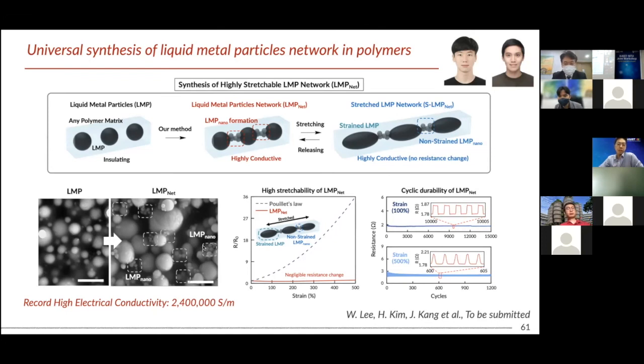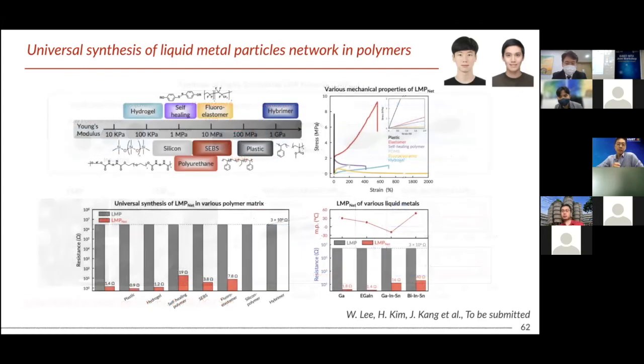And this resultant network showed really negligible resistance change up to 500% strain, and also very nice cyclic durability, more than 1,000 or 15,000 cycles. And this method is quite general, not only applied to a particular polymer matrix. We can apply this synthesis to silicone elastomer, SEBS, or polyurethane, even hydrogel, or even the very hard epoxy system.